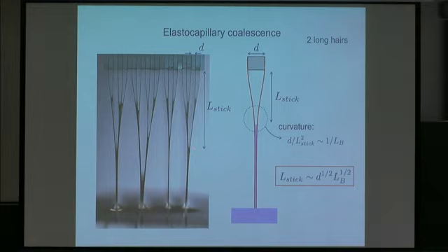And what you see is that the clumping mechanism relies on the association of two small lamellas that later on associate with another object, which later on associates with another object, and so on. So you have a kind of cascade of coalescence, where you have pairs of lamellas that connect with bundles, which connect with bigger bundles, and so on.